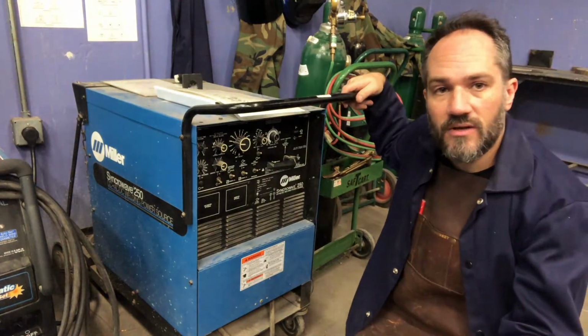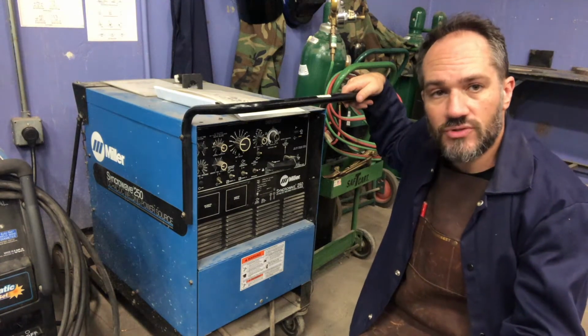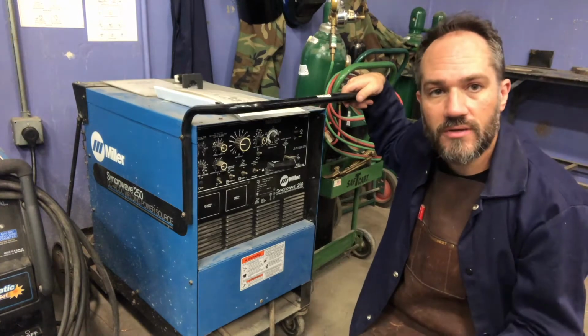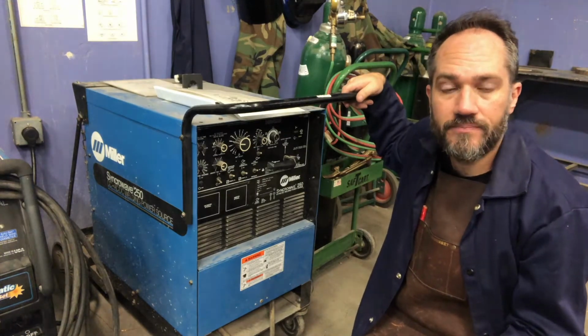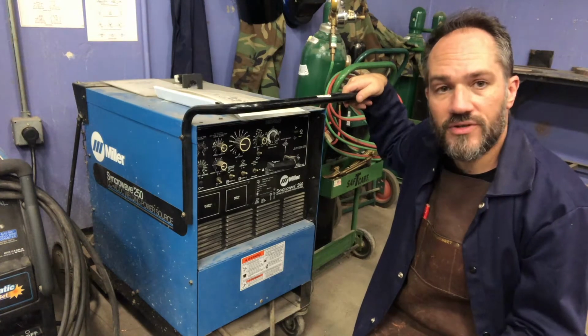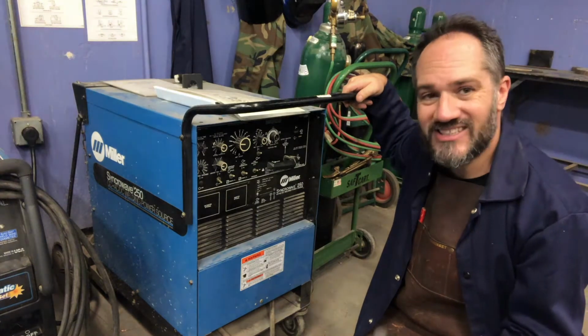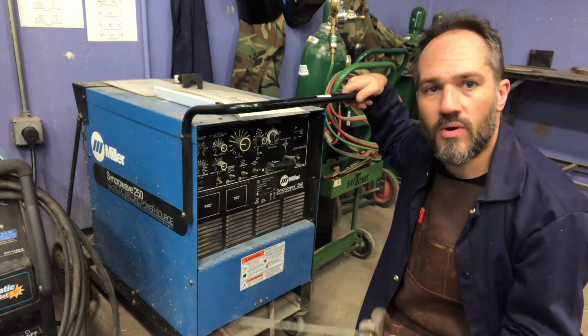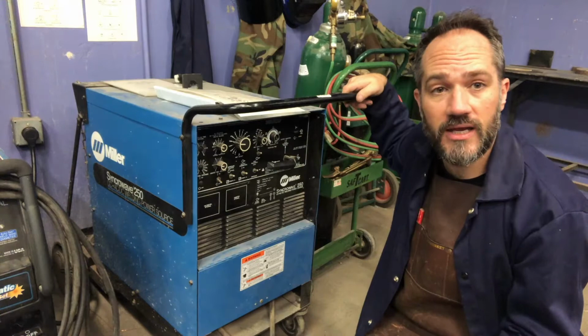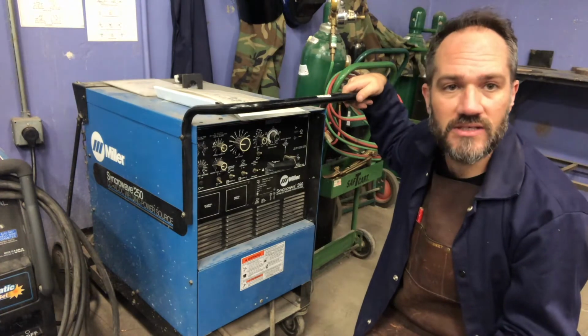If you're using very thin metal and you try to weld and it burns right through it, then you know it's set up too high. On the other hand, if you're using something that's fairly thick and it just doesn't seem to be sparking, or it's splattering a lot and you're not getting a good weld, then you need to crank it up a little bit.